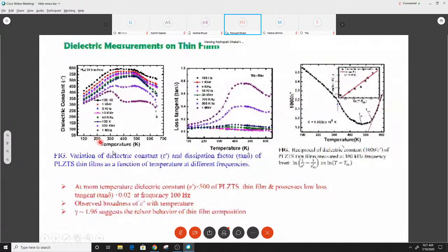Similarly, we have analyzed the dielectric behavior of the thin film compositions with temperature. It shows a broad range of dielectric constant with temperature. It shows the relaxor behavior, and further we analyzed with the modified Curie-Weiss law, and we obtained a gamma value equal to 1.96. That suggests the relaxor behavior of the thin film compositions.